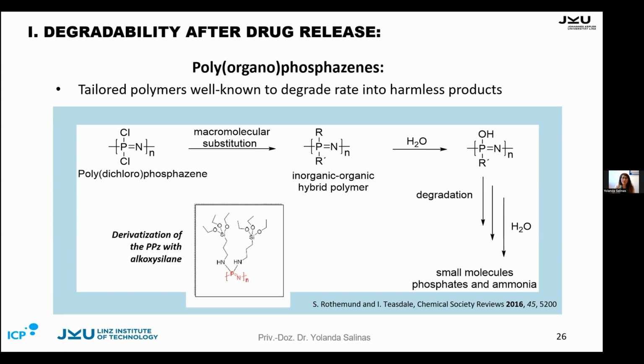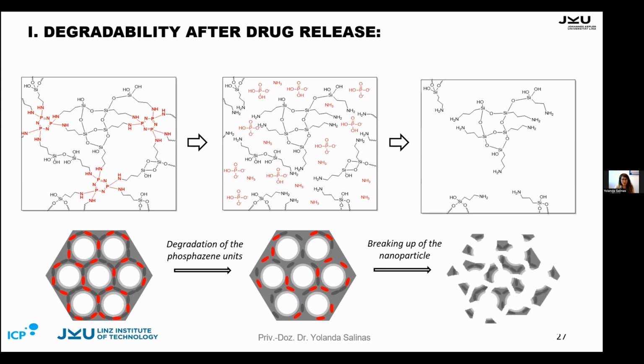But to be used with our nanoparticles, our silica particles need specific alkoxysilane linkers. So in this case, we derivatize the polymer and attach alkoxysilane units on one of these phosphorus atoms. Based on this, we have a particle that contains the silica units and also the phosphazene units, which are degradable. Therefore, under specific conditions, these phosphorus linkers will start degrading, and the polymer helps in the disassembling of the nanoparticle. So the particle will break up quickly.